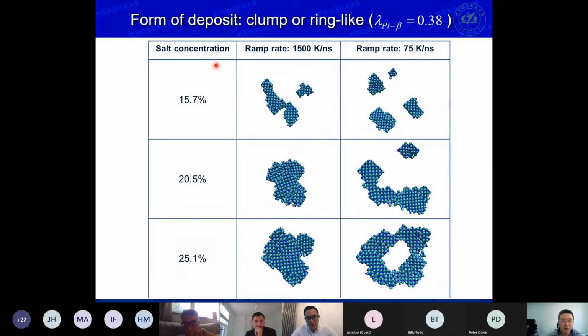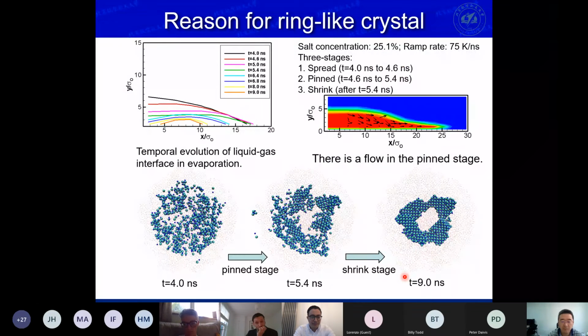As you can see, we simulate different salt concentrations and different ramp rates, that is, how quickly the temperature increases. If the ramp rate is quicker, we get the clump pattern. But if the evaporation is slower, we can get the ring-like pattern. The reason behind this is that in the evaporation there is a pinned stage, and the contact line is pinned on the surface, and there is an internal flow from the center to the rim. Because of this flow, the salt ions can flow from the center to the rim and finally form the ring-like pattern.